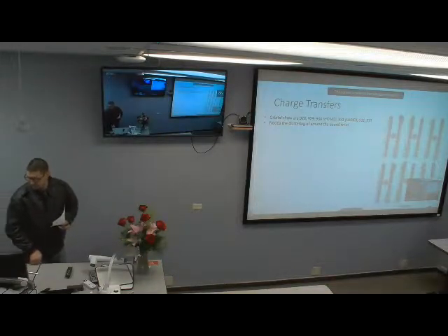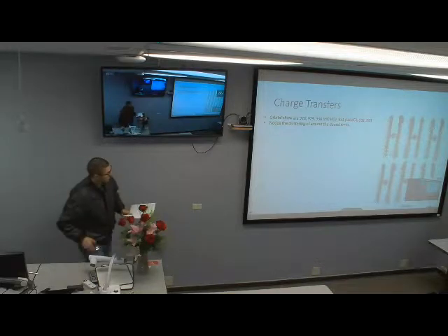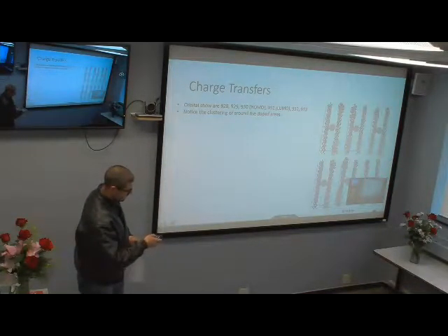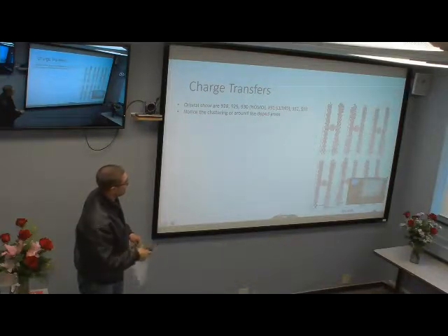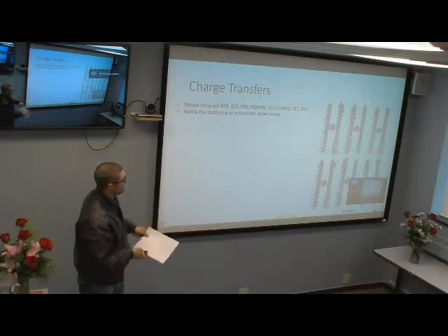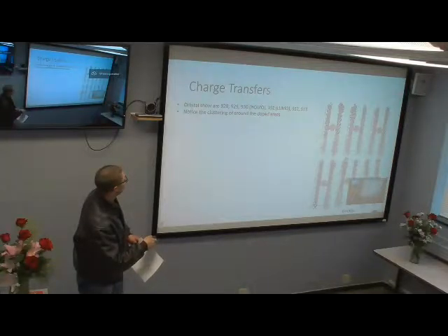And this should be the electron densities in the ground state for that specific image. For charge transfers, I really wish I would have been able to get the HOMO and LUMO and all these images for the system when it was heated, and then go beyond just a couple above and below HOMO and LUMO to demonstrate what happens with the gold nanoparticle. But you can already see, bouncing around the HOMO and LUMO, how the charges in the electron orbitals transition from the N to the P material. So across that gradient, you're going to have different parts of the structure hovering right around what it would need for the electron to pass from one orbital to the other. The orbitals shown here are 928, 929, the HOMO orbital 930, 931 LUMO, 932, and 933.